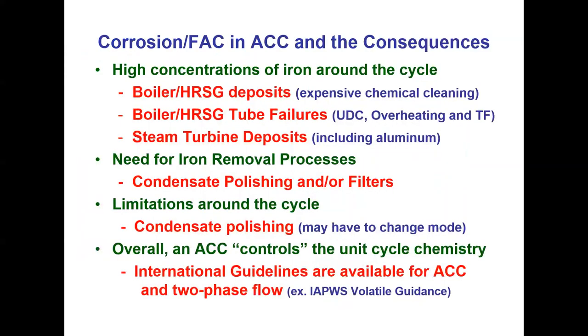And what we've found over the years is that this corrosion, FAC, as we call it, has a number of consequences. The main one, of course, are the high concentrations of iron around the cycle, which leads to boiler and HRSG deposits, perhaps having expensive chemical cleaning. It leads to tube failures in these systems, boiler tube failures. Under deposit corrosion is probably the main one. Some overheating due to heavy deposits and thermal fatigue.